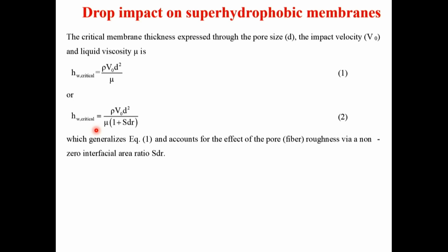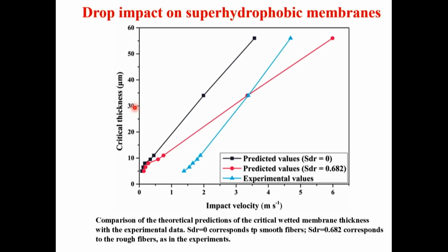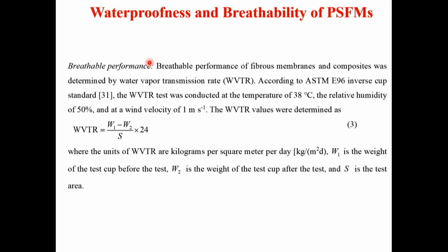So we tried to compare this simple prediction with experimental data, and the theory is very simplified, imperfect, but all in all, what you see here, first of all, is that porosity and roughness are definitely helpful, and for a certain value of roughness, our prediction goes this way. This is essentially the critical thickness which stops penetration for different velocities in the range of water droplets. So the prediction goes this way, the experimental data goes this way. The agreement is definitely not great, but at least the trend is caught, and this shows that you can make something waterproof, but the thickness should be high enough, about 10 to 50 microns of this type of fibers, to protect against rain, for example.